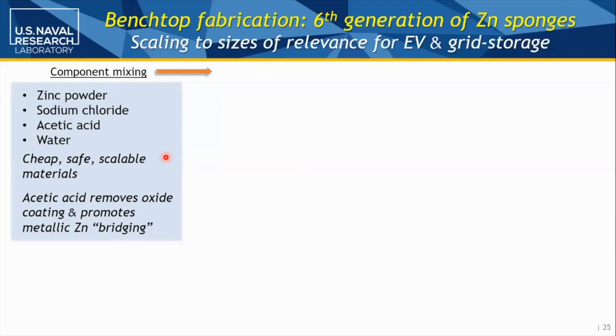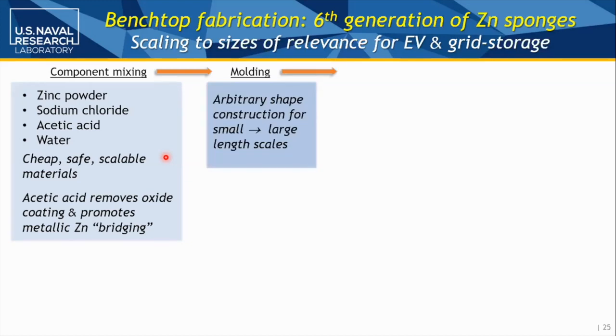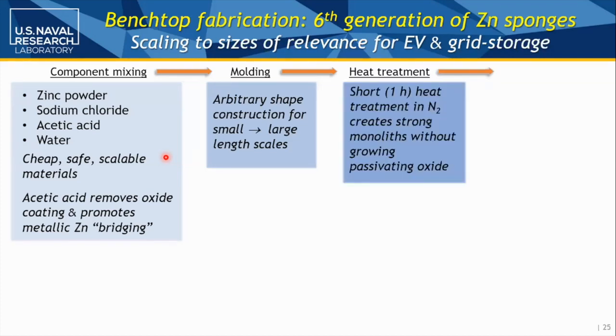And a new postdoc, Ryan DeBlock, we're about to hire. He's tried to make this even faster and more scalable, and it's giving you some control on how much zinc oxide is on the surface. So now he's got zinc powder, salt, acetic acid, water. You could still keep the arbitrary shape construction we had with the emulsions. The heating is much shorter.